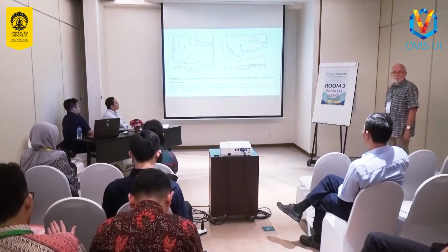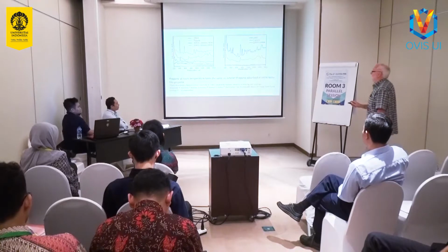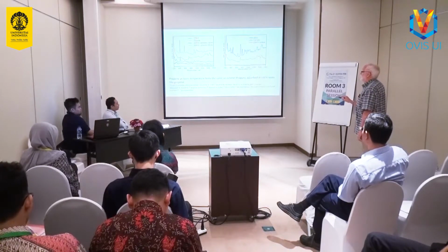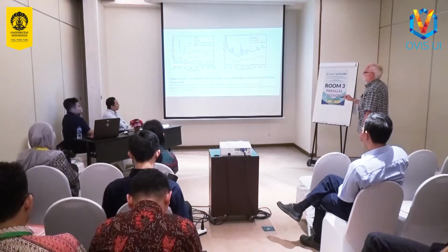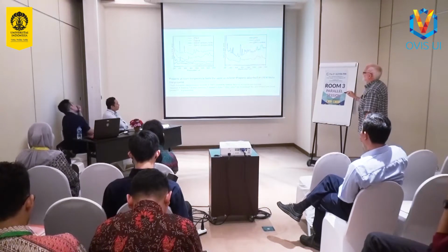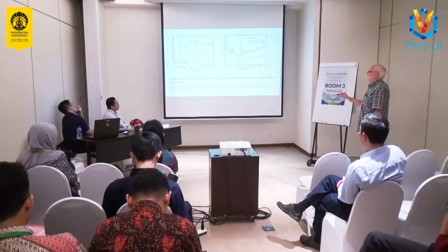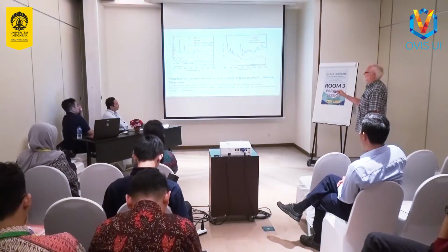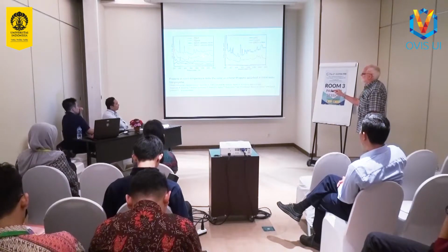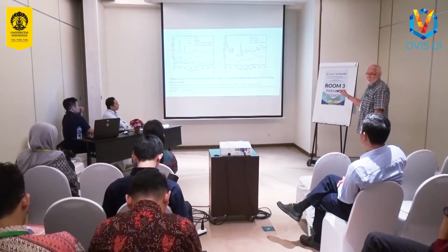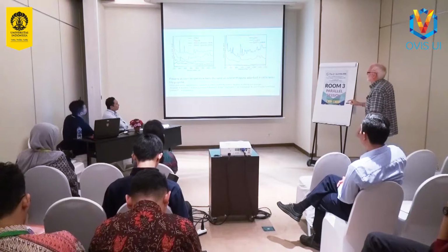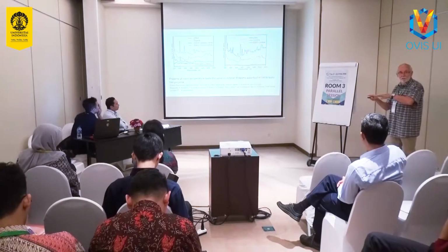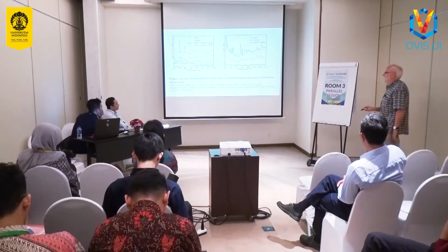And the same thing happens with propene. We put propene in at room temperature. Again, this is the octene spectrum over here for comparison. This is propene. There's the blank zeolite. There's the propene. The red one is propene put in at room temperature. This one was exactly like the red one here. So propene and 1-octene are making essentially the same thing at room temperature when we put them in the zeolite.